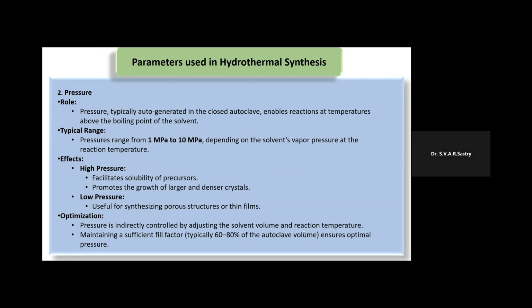The next parameter used in hydrothermal synthesis is pressure. Pressure is typically auto-generated in the closed autoclave. It enables reactions at temperatures above the boiling point of the solvent, and the typical range of pressure is between 1 megapascal to 10 megapascals, depending on the solvent's vapor pressure at the reaction temperature.